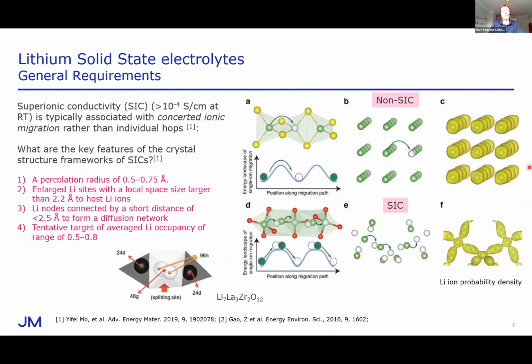So back to electrolytes. What do we need in a good electrolyte material, apart from the fact that it needs to be formed into a dense ceramic piece? We need superionic conductivity for a starter. This is roughly or loosely defined as conductivity above 10 to the minus 4 Siemens per centimeter at room temperature. And what sets a superionic conductor apart from a regular ionic conductor is its capacity to facilitate concerted ionic motion through its lattice rather than a series of individual hops.